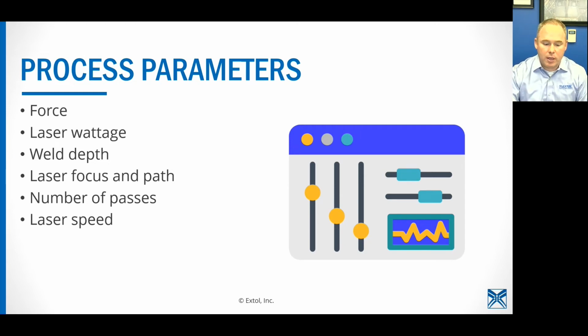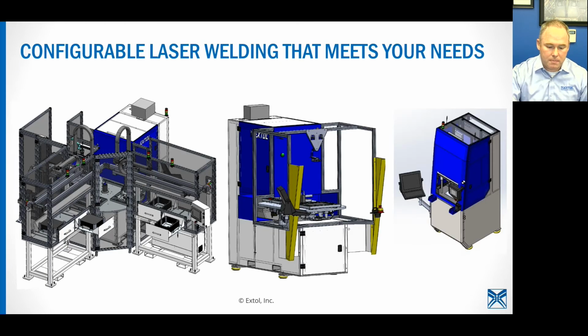That weld depth is really important. We do a closed loop control around weld depth, and it's totally application specific. We've had a really compliant part where we couldn't really use weld depth, but we used vision to make sure we had a good weld rib for that particular application. Usually depth-wise, we're running around a millimeter or so, give or take. If it's a really small part, we might be using 0.2 millimeters. That really small part was actually 0.2.